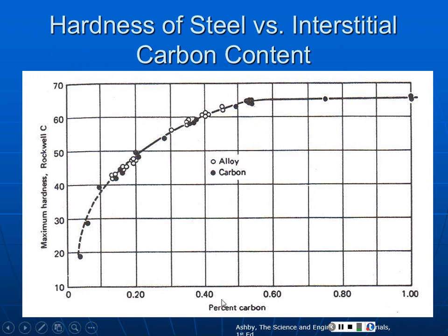And we find carbon, of course, is the perfect model for this. You've already seen this once, and I told you we'd see it again. This is very important that you have a general sense of what's going on. As we add carbon, your Rockwell hardness rises, and it reaches saturation. Now, why does it do that? Because after you get to a certain level of carbon, almost all of the unit cells are going to be distorted by that carbon that really doesn't fit very well into the structure of iron. And that distortion is going to make dislocation movement very difficult. And adding additional carbon doesn't fundamentally change that difficulty because everything's already distorted at that point. So that's the saturation point that we get.